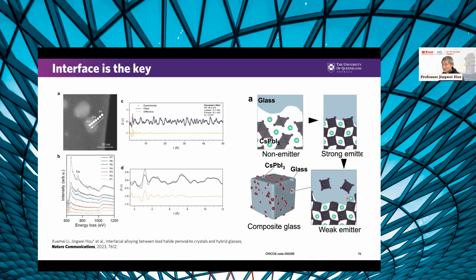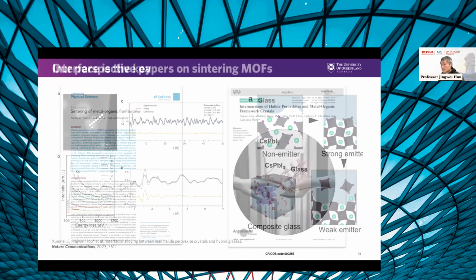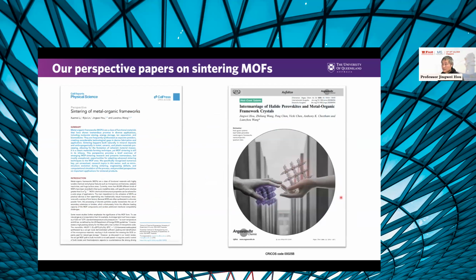This dissolution process can make the material healing the defects at the interface. That's why we are seeing a huge increase in terms of the efficiency for the perovskite. So that's really, really interesting. And also on this topic, we published 2 perspective papers, so any of the audience who are interested can have a read.